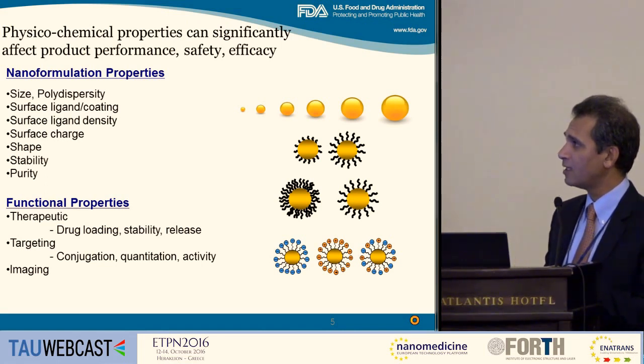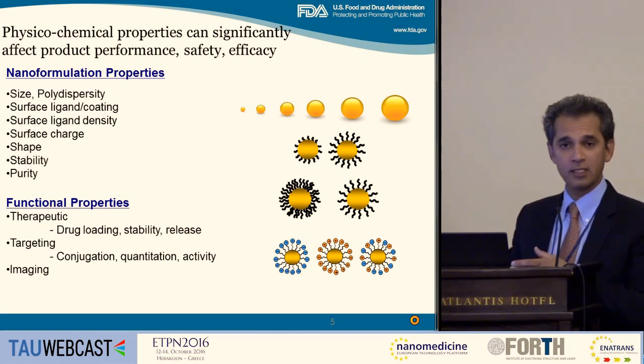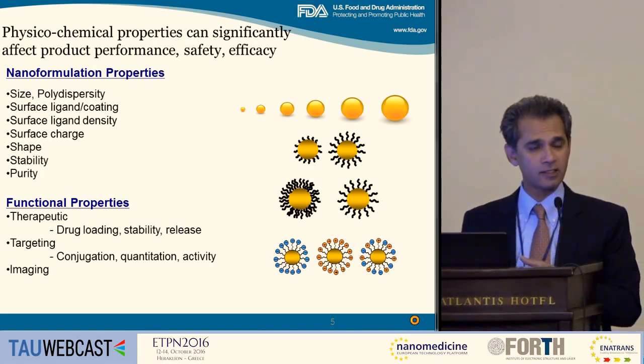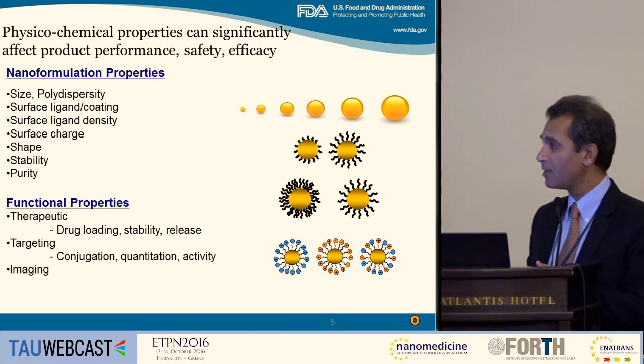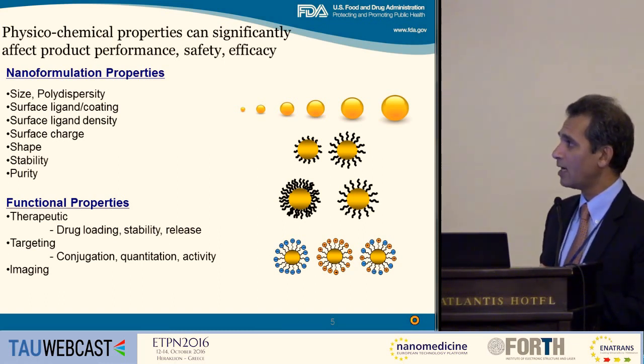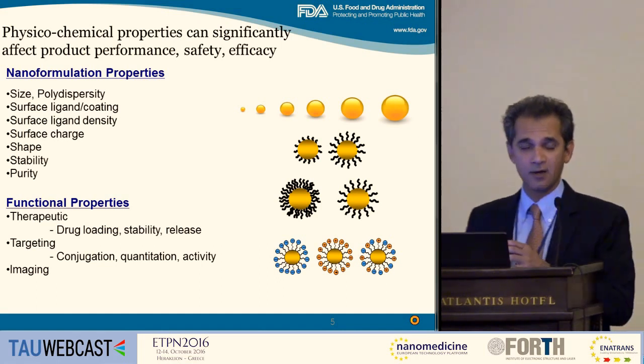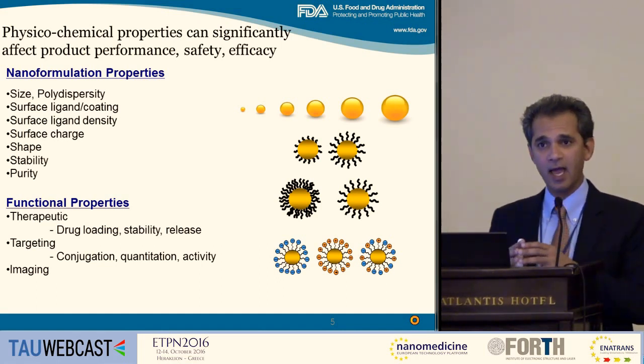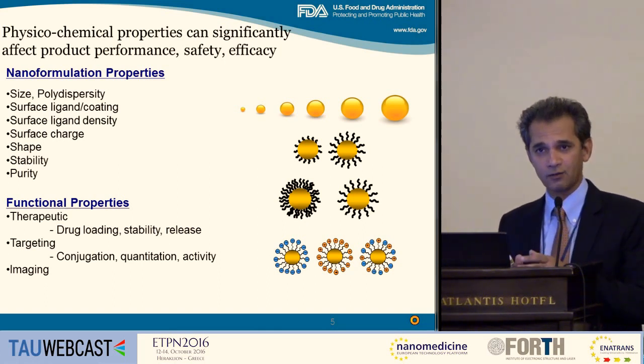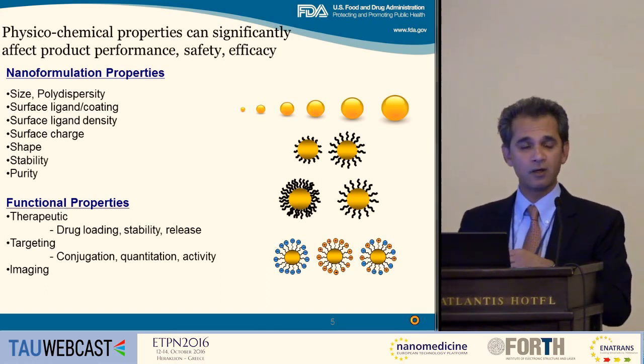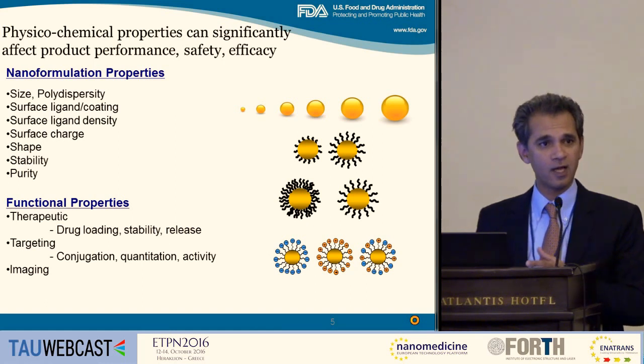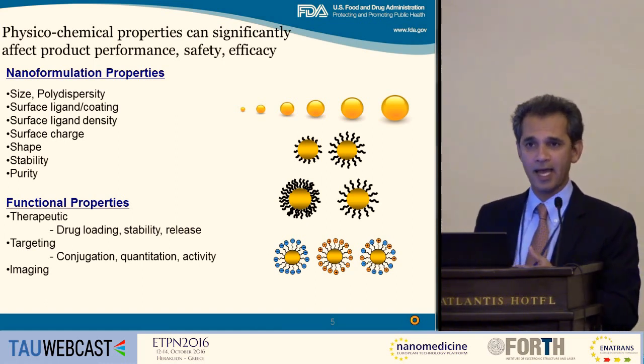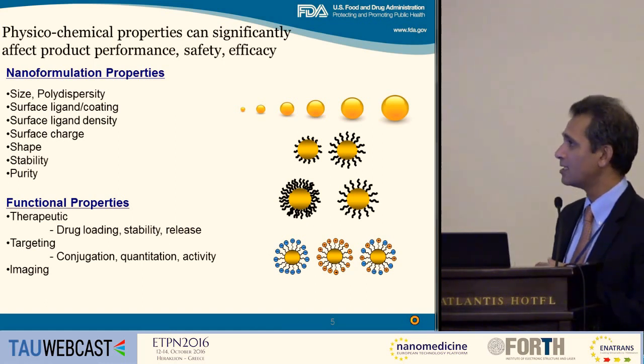Shape, we have seen some things with shape beyond the plasmon resonance, for example, for gold nanorods and such. Your biodistribution may be affected by shape, stability of the coating. What we have seen in some cases is the stability of the coating is critical. You may have the coating when you manufacture it, but then down the road, the coating may come off 6 months down the road. And that has tremendous impact in the safety and efficacy.